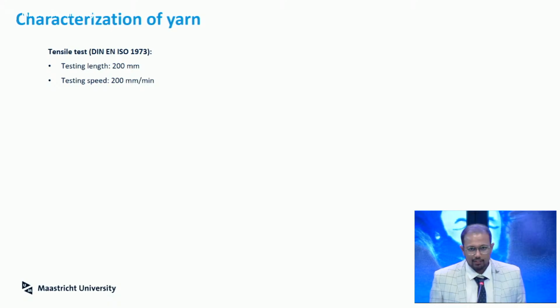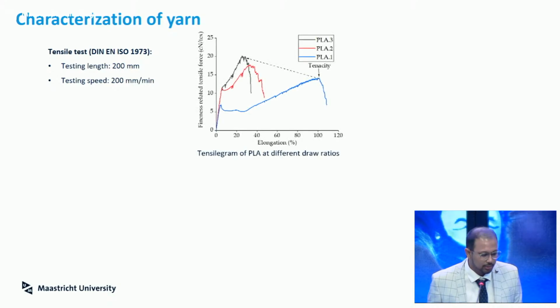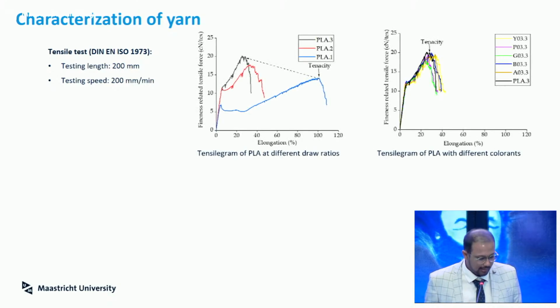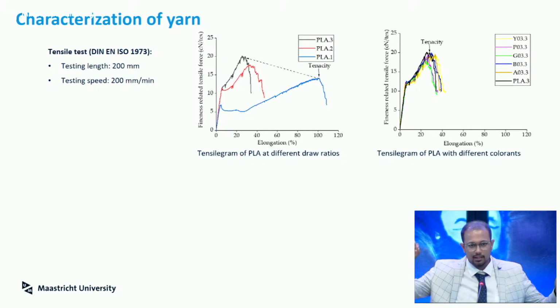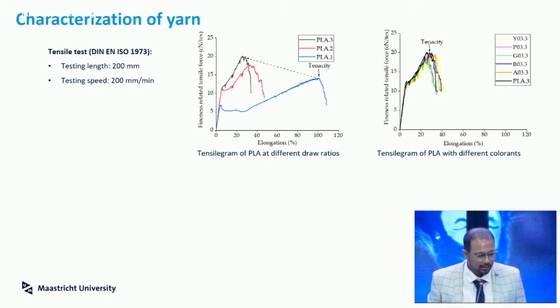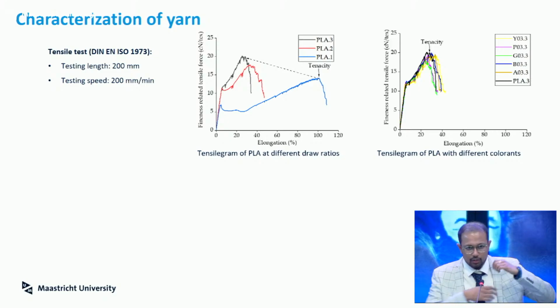After I made this, of course, you need to test if it is good or not, or you have to have a comparison to see whether it is performing better than the pure material, or whether my colorant is leading to some issues. That is what I did by doing some tensile tests, which is nothing but pulling the yarn and testing how much load it can take. On the left-hand picture, the tenacity is the ultimate tensile strength of the filament, and I used 3 different drawings. So I had 3 different speeds with which I was drawing the yarn, and as you can see in the picture, my strength and my elongation varied depending on how much I was drawing it.